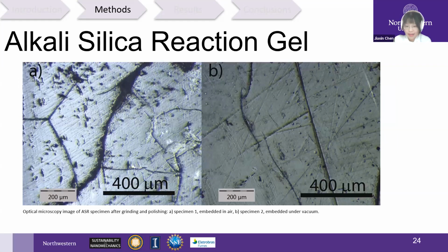The previous slide mentions epoxy embedding to contain the shape of the ASR gel. I will provide more details here. Each ASR gel specimen was embedded in a 32 mm cylindrical mold filled with epoxy cure resin. Epoxy embedding is used to provide structural support and facilitate the metallographic polishing phase. The first specimen is air embedded, on the left-hand side, which means we embed our specimen at room temperature in normal conditions, as shown on the left-hand side.